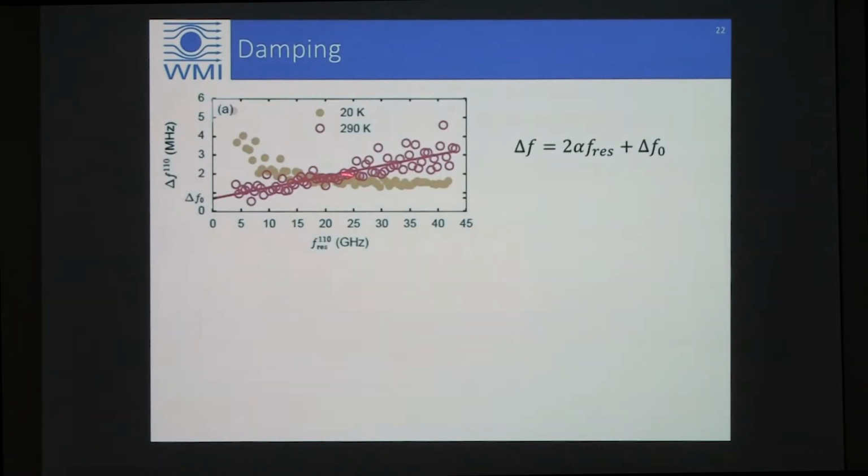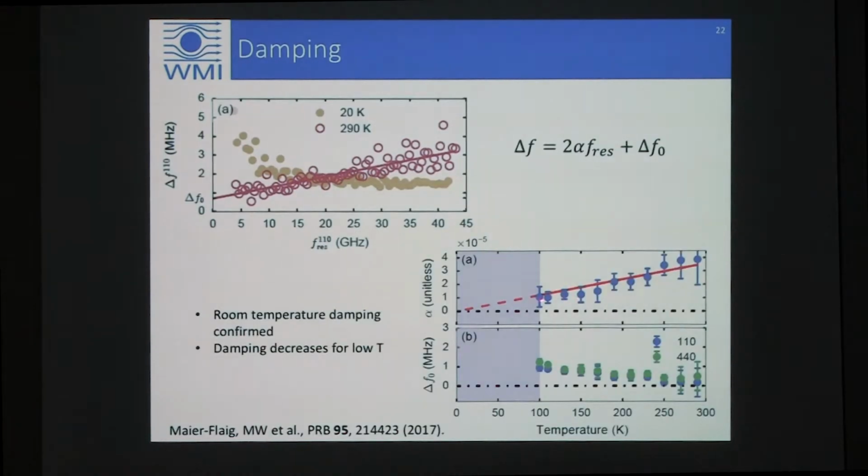Yeah, with negative slope. So what I'm saying is, what you're seeing in here is a peak towards low temperatures, right? Which is a slowly relaxing impurity. And if you go out to high enough frequencies, then eventually the alpha wins, right? And it will be a positive slope. The problem is we cannot go so high. You can see from this plot that at 20 Kelvin, right, the slope is essentially 0. The Gilbert damping is completely switched off by going to such low temperatures, right?